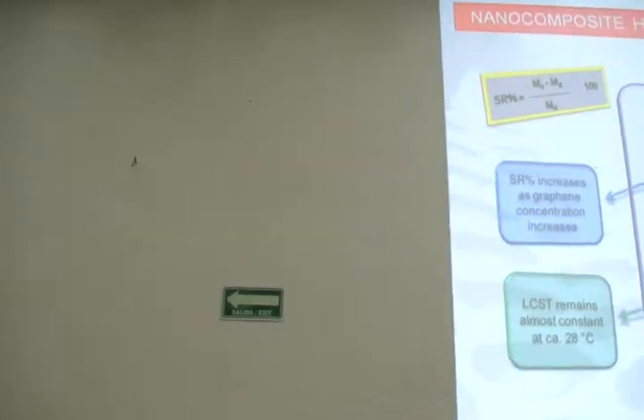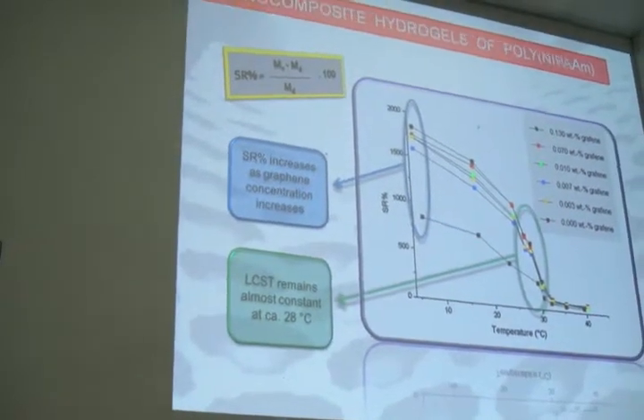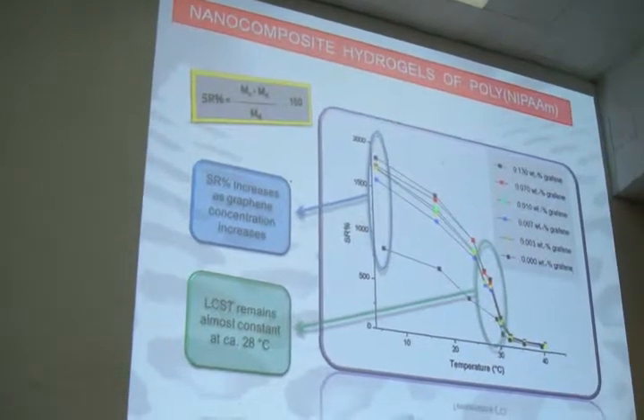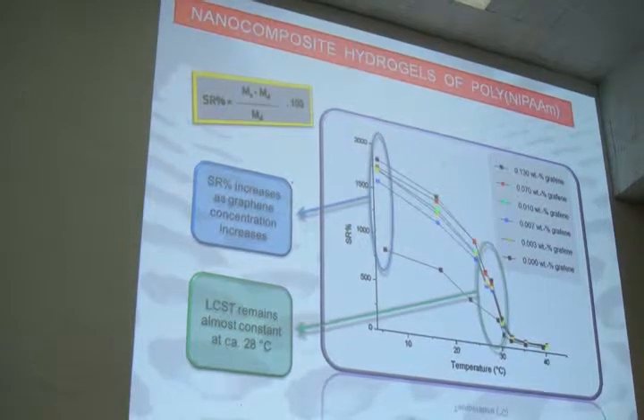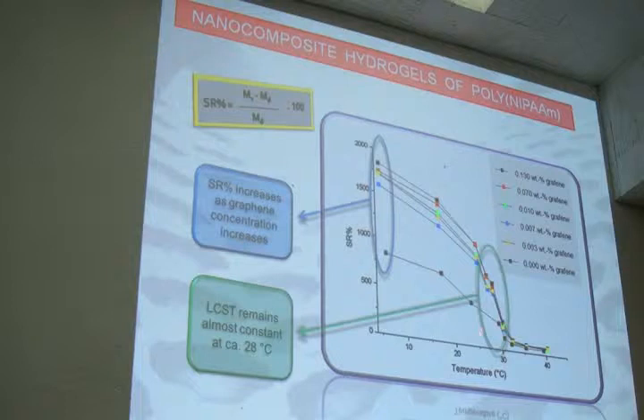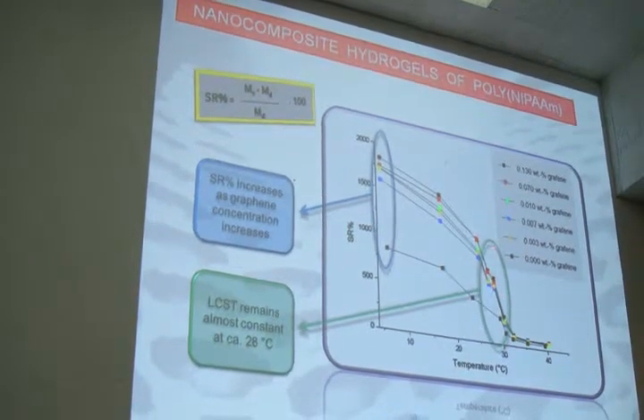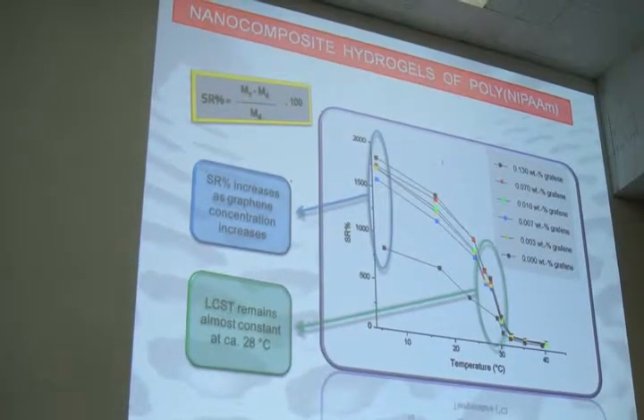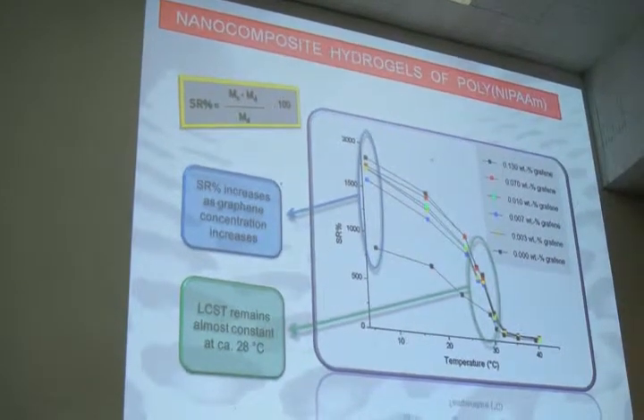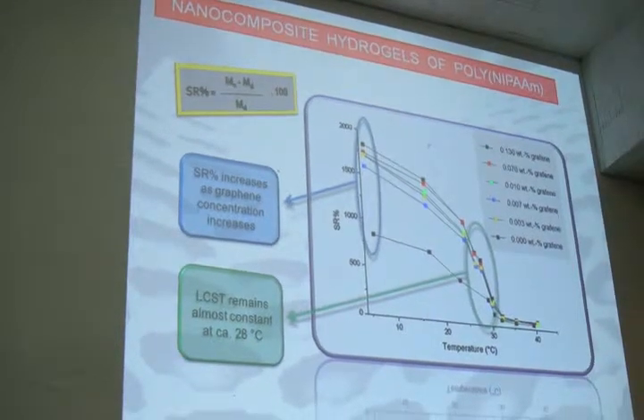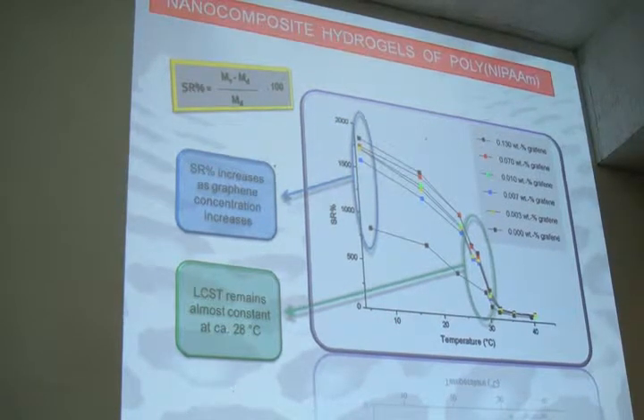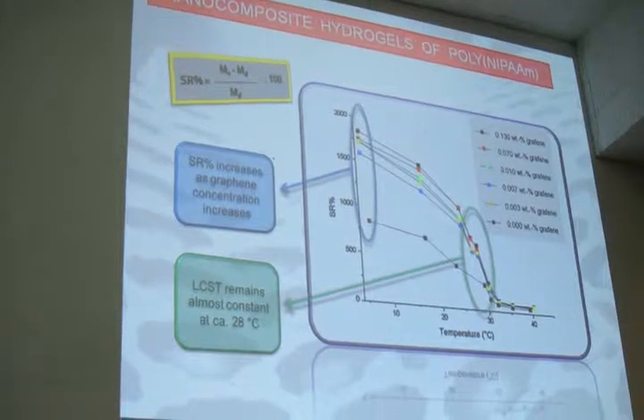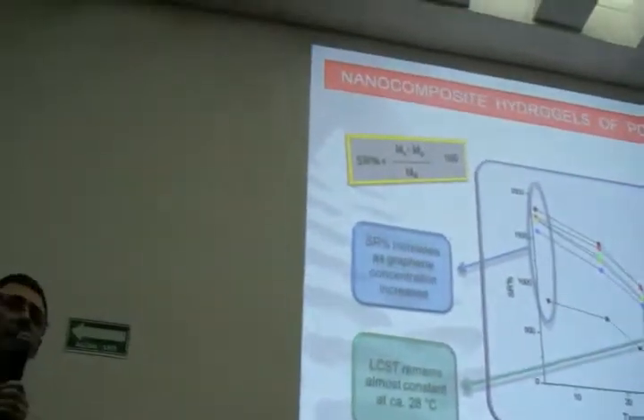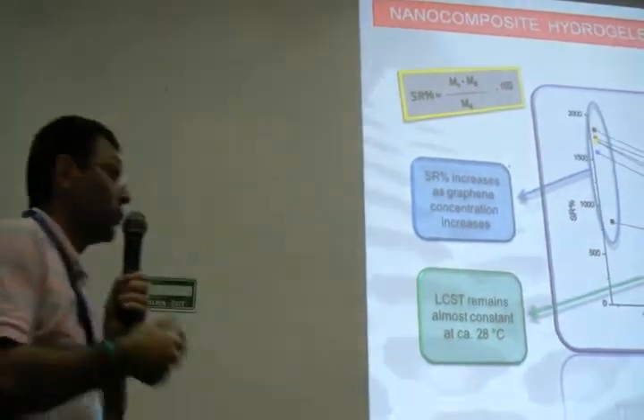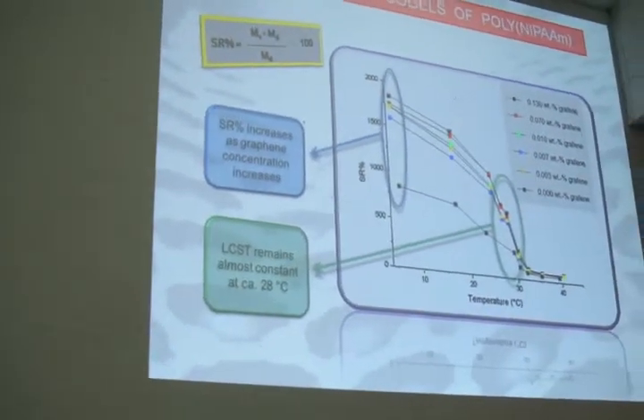Okay, go a little bit faster. What about the swelling behavior? We are talking about hydrogels with a lower critical solution temperature, and so we are interested in these aspects. This is the neat polymer hydrogel without graphene. You can see the LCST at about 30 degrees, and the LCST is not affected by the presence of graphene, but the amount of swelling is strongly increased, even for a low amount of graphene. It is a common behavior which we are finding. This is probably due to the fact that a layer of graphene can obstruct the possibility of cross-linking between macromolecules that are placed on the different faces of the same layer. So the cross-linking is lesser and the swelling is larger.